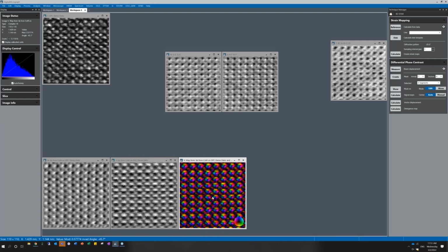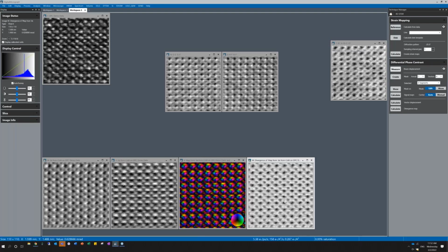So this is a vector image. If I scroll on the image, you can see at the bottom left here in the ribbon, the modulus shows the magnitude of my beam displacement vector, which is in milliradians from the diffraction images, and also you can see the angle. And the angle corresponds, as you can see here, from the color wheel, to the direction of the beam displacement vector map. So these are the atomic columns, and you can see the beam. So, for example, here with this purplish color, it means that the beam displaced in that direction, which is opposite to the electric field direction. And as I said, from this beam displacement vector map, you can calculate the electric field vector map. And if you get the divergence from this map, you can calculate the charge density from the divergence map in your sample as well.